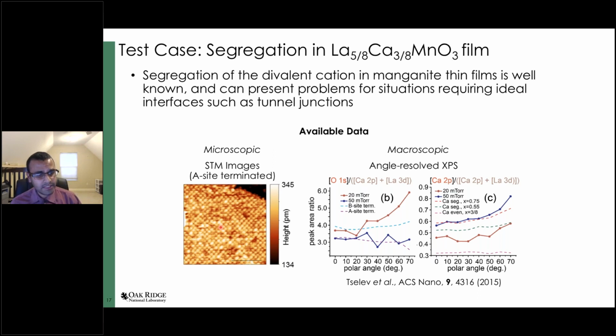The other thing that we have for this particular sample is angle resolved XPS data, which is shown here and published in this particular paper. What it shows is that we have calcium segregation as you get towards the surface. And this is a known feature of most manganites. There's a tendency, because of electrostatics, that calcium will migrate to the surface, and there are also strain-related reasons for this. But nonetheless, we see this kind of segregation of calcium towards the surface, okay? So how do we combine the information that we have from atomically resolved imaging, as well as this kind of macroscopic information that comes from XPS, in our particular model?